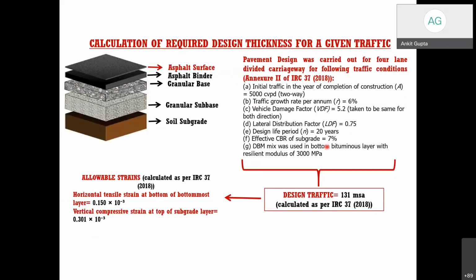Now we have designed the traffic as per these values, and we find out that the design traffic is 131 million standard axle. Okay. Now for the given distress models, that is the rutting and the fatigue models, we find out the horizontal tensile strain at the bottom of the bottommost bituminous layer is 0.15, or you can say 150 micron, and vertical compressive strain at the top of the subgrade layer was 301 micron. Okay, so these are the values which we have found out.